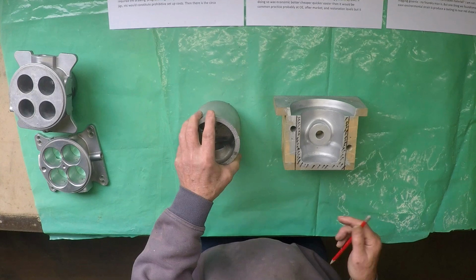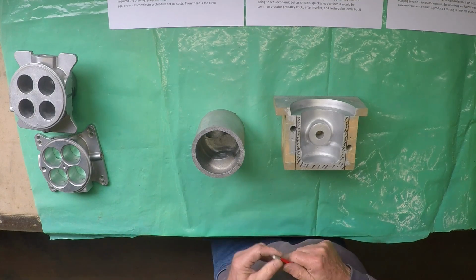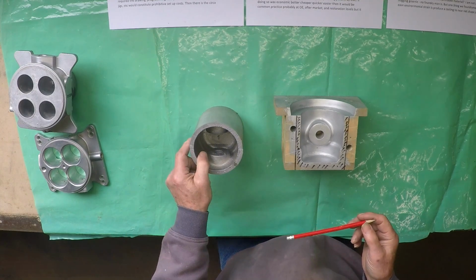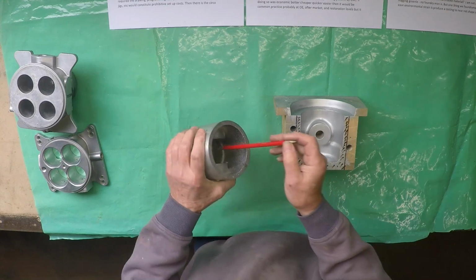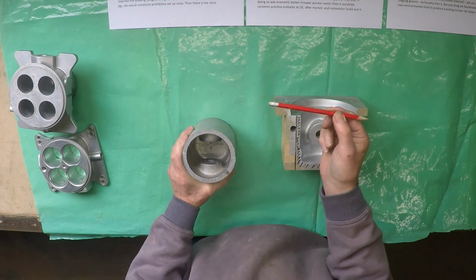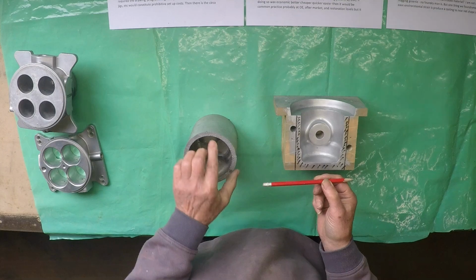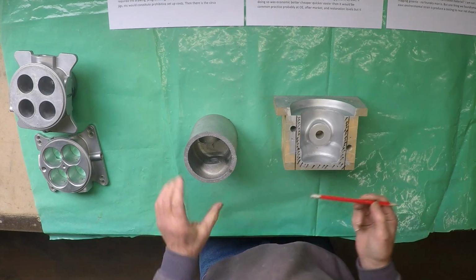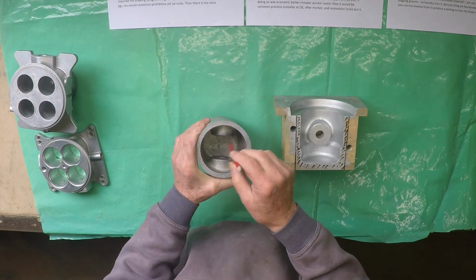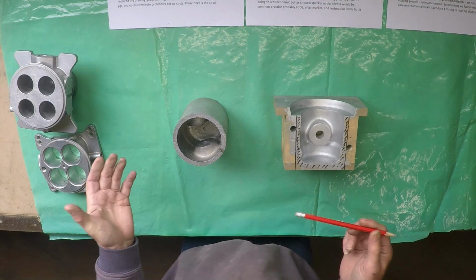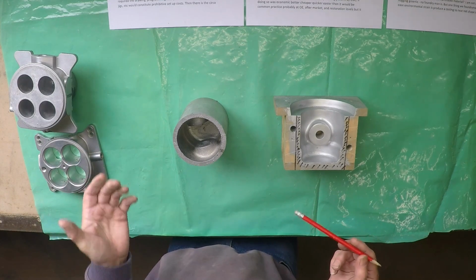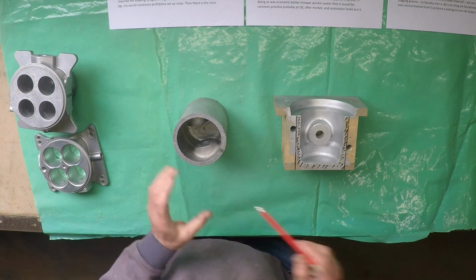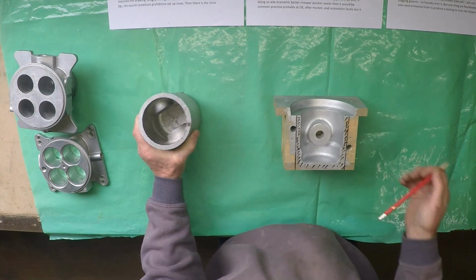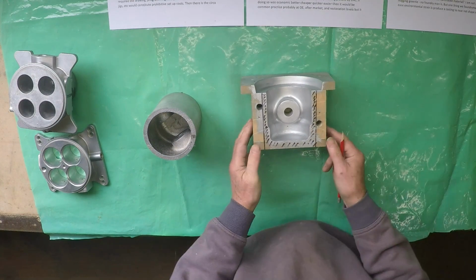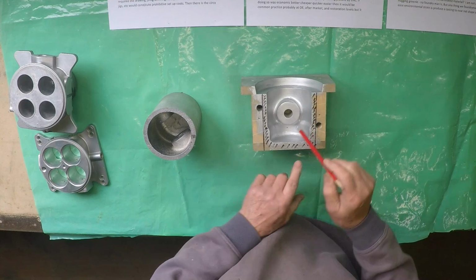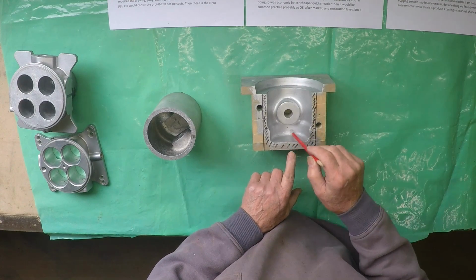This is fairly large. The main impediment to machining is that the inside of this piston has to be machined 100mm deep through a 90mm hole opening, and all while you're dodging around these gudgeon pin bosses. The difficulty is in getting tools to cut under the gudgeon pin area, and if we look at the core box we can get a better look at it. I mean, we've got to cut this area down in here.